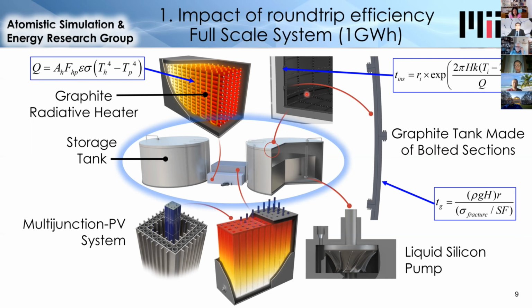Going to the next part of the image, we have the tank wall. And so you can see these individual elements, they're about 1 meter in size for a 20-meter diameter tank. And this is because this is about the largest size that graphite is manufactured. It wouldn't be practical to make the entire tank out of one piece. So instead, we have individual components that are bolted together using carbon bolts. And so a key equation used in this case is the stress developed in the wall by the pressure of the fluid from gravity. So the wall has to restrain that.